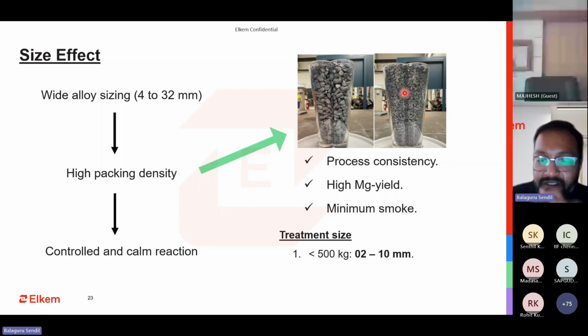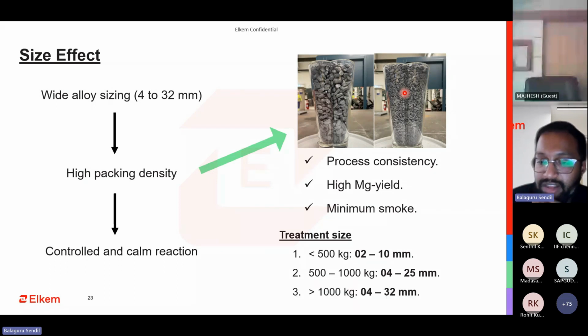And the treatment size. This is a typical thumb rule that Elkem follows globally. If the treatment is about 500 kgs, then we go with 2 to 10 mm. The pocket, we will design it correctly and give it at a low addition percentage. We'll give you the FSM with correct rare earth and correct calcium. If it is about 500 to 1000, we use 4 to 25. And the last, if it is greater than 1000, we go for 4 to 32 mm. So this is the impact of size.